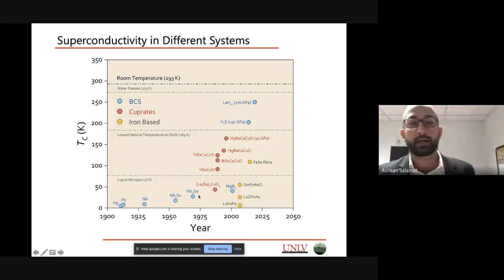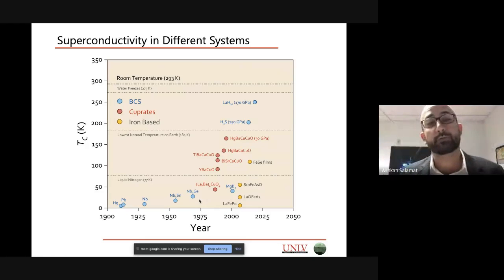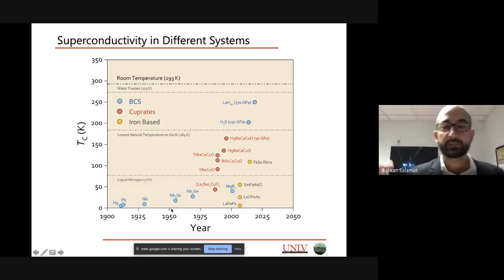However, as time has evolved, we as scientists have developed weird and fanciful, wonderful and powerful protocols to make compounds that have reasonably high superconducting transition temperatures. So here we're looking as a function of time since the discovery by Onnes in 1911 against the superconducting transition temperature. And so for the first 60 years, we only really measured the elements, and the superconducting transitions were very, very low, below 10 Kelvin.